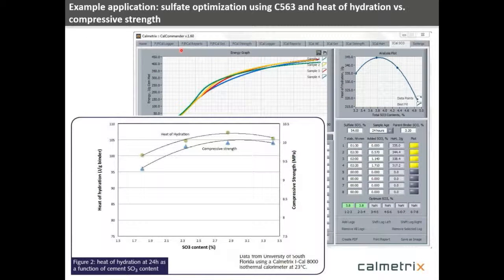And finally, the last one I'll mention is the ability to use the calorimeter for sulfate optimization. And if you look at this curve down here in the left corner, you know that the compressive strength in concrete is a function of the sulfate content, and that there is an optimum sulfate content that gives you the maximum strength. And if you put more sulfate in or less, you go on either side of that peak. So there's an optimum sulfate content. You put more than that in, you're wasting money. If you don't put enough in, you may not develop enough strength. Well, as it turns out, if you look at the heat of hydration in joules per gram, so now we're using the fact that we can quantify the data, the shape of that curve is similar. In other words, it has the same relationship.